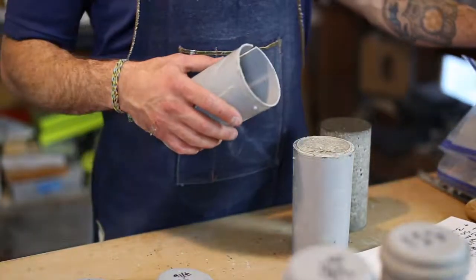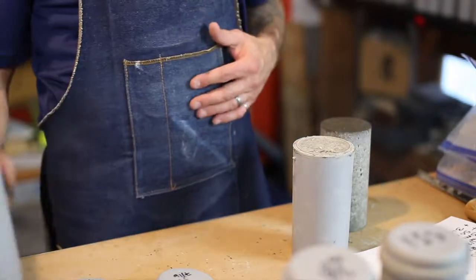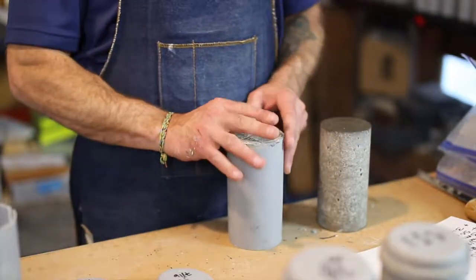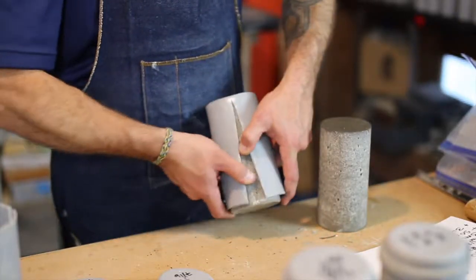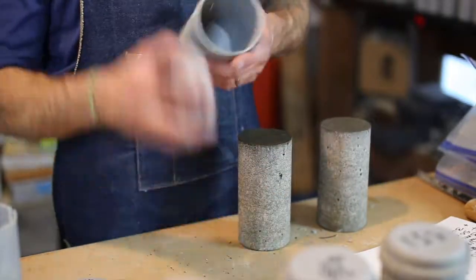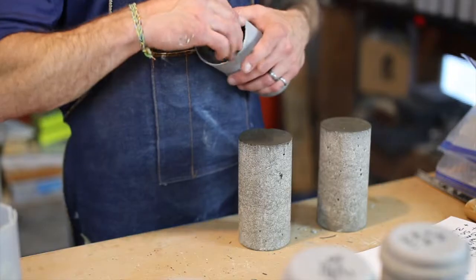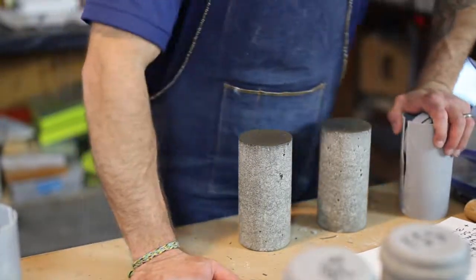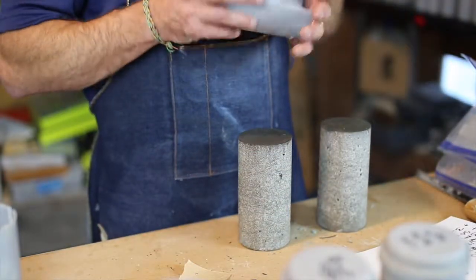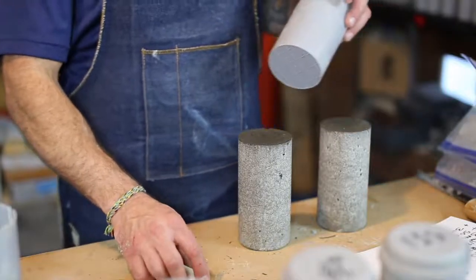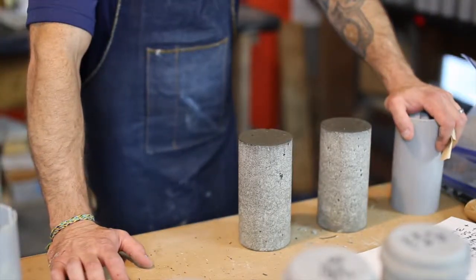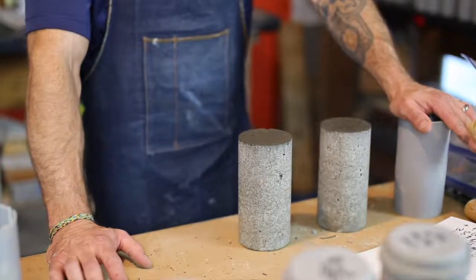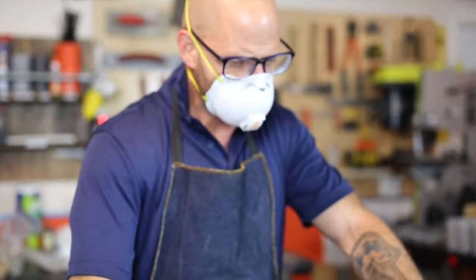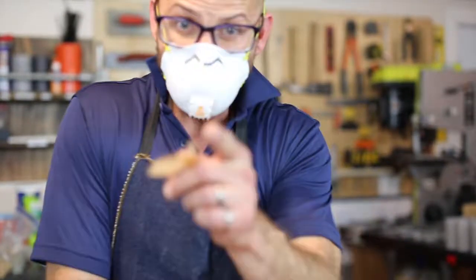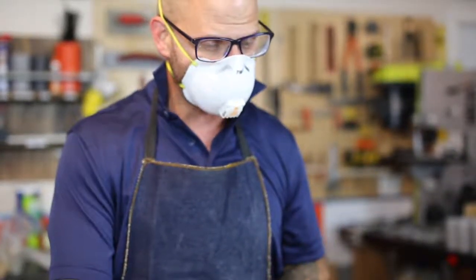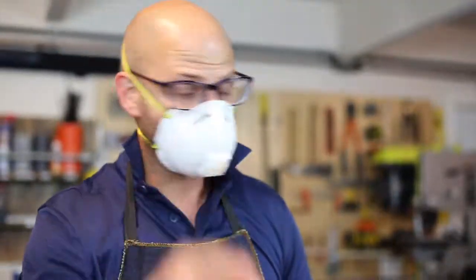So we had 18 pounds of dry, 570 grams of H2O. We had 1.54 pounds of an alternative binder called Juno, which made about 8% of the total cementitious, 4 mils of a high range, 8 mils of a non-chloride accelerator, and 10 mils of a densification agent, a nanotechnology. So we ended up adding a little bit more of each, but our slump was 4.2 inches in a nice temp, 70 degrees, and we're going to run those breaks today. And again, this is the Goodcrete 1101, what I like to call the post-hole concrete. Let's go break some concrete.